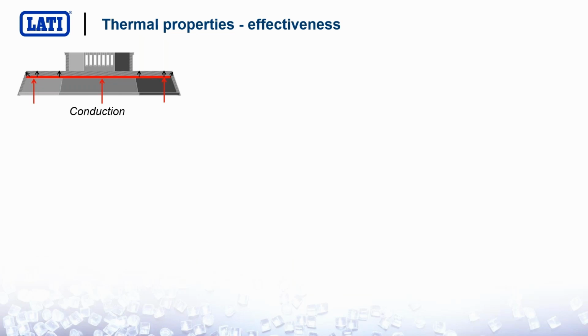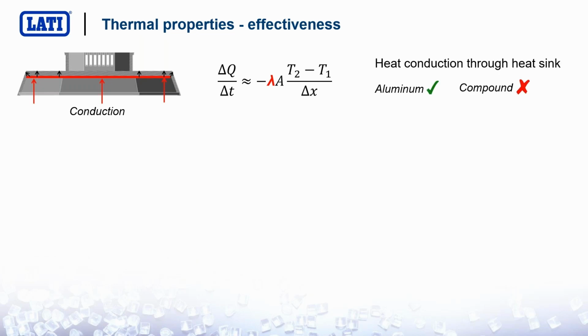So the first step is to move heat through the heat sink. We have to warm up the heat sink. So the first step is heat conduction. The law describing heat conduction through the body of the heat sink is described here. I do not want to get into the math, I know nobody likes math. But I want you to focus your attention on that red letter there, which is called lambda, and which is the thermal conductivity. Aluminum being a material with a much higher thermal conductivity, we can say that the first step is won by aluminum. So aluminum will perform much better when it comes to conduction. So the aluminum heatsink will warm up in a much shorter time than the plastic compound.